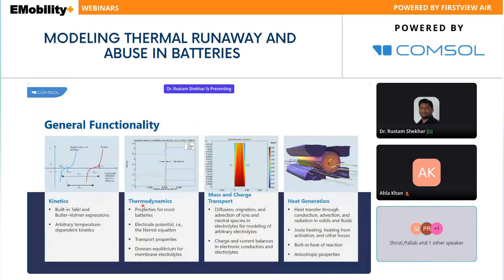So now, fundamentally, how will it approach the battery models? We told you that there are multiple approaches, but how does this approach look fundamentally? So you are taking care of the kinetics. You are working with thermodynamics. This kinetic and thermodynamic pair will give you the feasibility and rate of the electrochemical reaction. And then you add the mass transport and charge transport, which will be done by diffusion, migration, and convection, in case there is any advection happening, and you can account for the charge and current balance. That means it will be following all the conservation laws, and then you add the heat transfer to it, which will give you the complete picture, which we talked about in the previous slide.